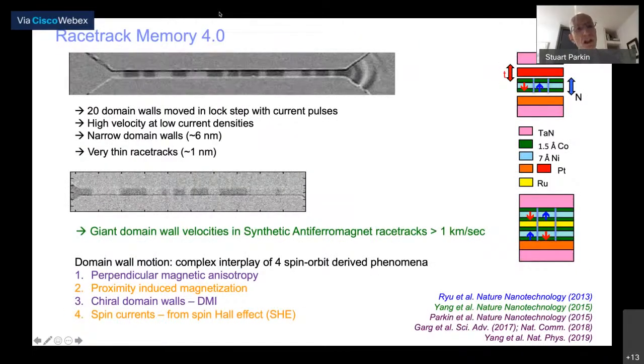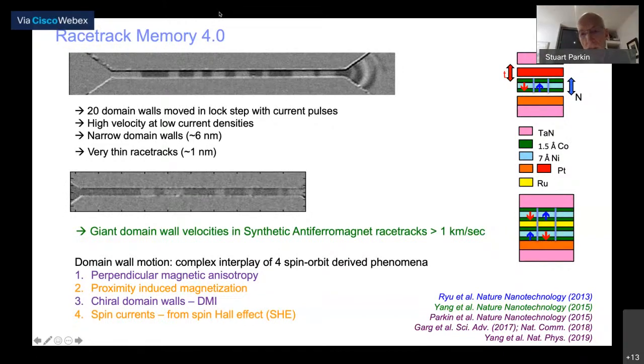Just to show you what this looks like, in this case we're using magneto-optic microscopy, which is basically reflecting polarized light from the surface of the racetrack and detecting the change in the polarization of the light. At the top, you can see 20 domain walls that are moving at speeds of about 300 meters per second as we pass current pulses into the wire. And underneath, you can see the synthetic antiferromagnetic racetrack. I hope you can see the motion of the domain walls backwards and forwards, moving at a speed of just over 1 kilometer per second.